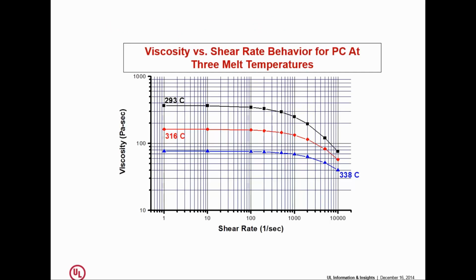Now, temperature is not trivial. If you look at a material like polycarbonate, you can see that the effect of temperature is a lot more dramatic than it is in a material like polypropylene. So you have to kind of work with what resin you're playing with. It's also important to understand that the hotter the material gets, the less efficient shear is in reducing viscosity. And you can see that in this graph. The polycarbonate running at the lowest temperature experiences a larger decline in viscosity with increasing shear rate as a percentage of where you started than does the material running at the higher temperature. So as you raise the melt temperature, you're lowering the effectiveness of the adjustment related to shear rate. So there's an interplay here between these two variables, and it needs to be well understood.